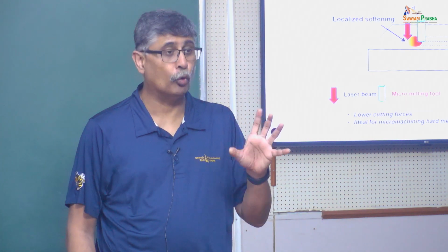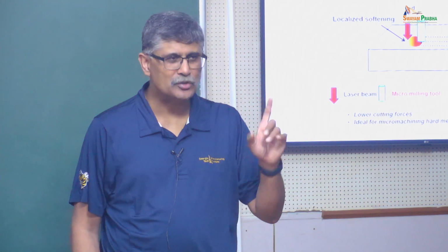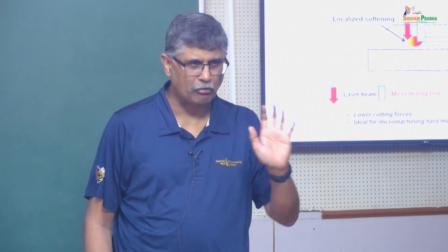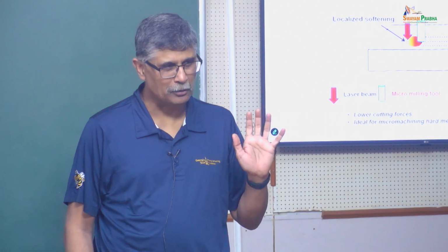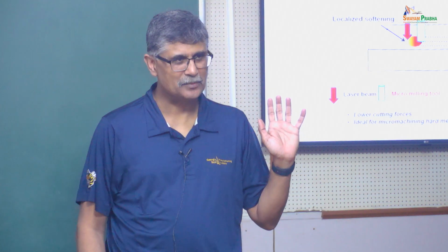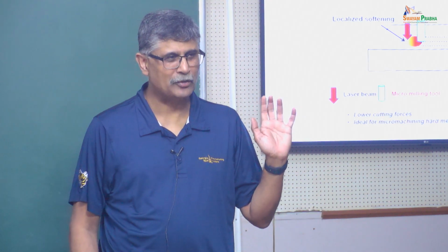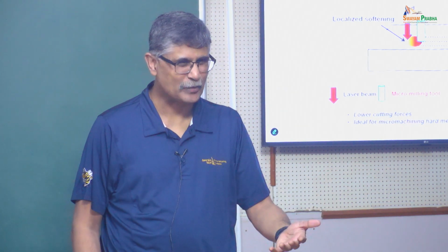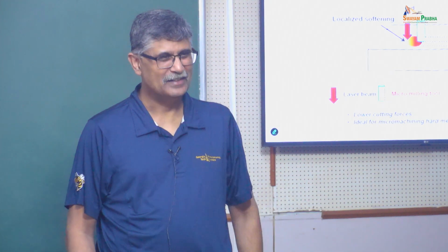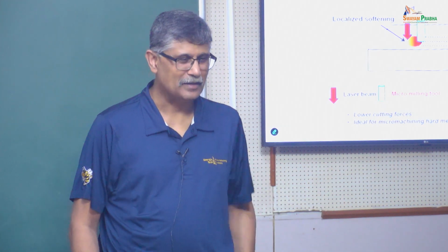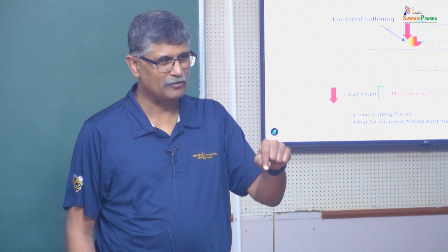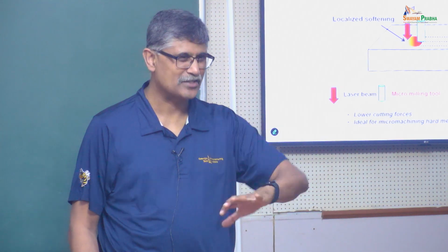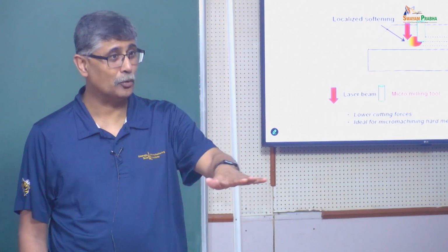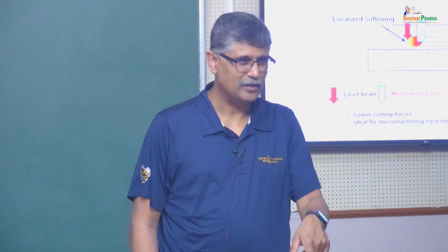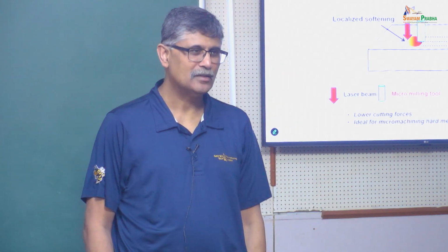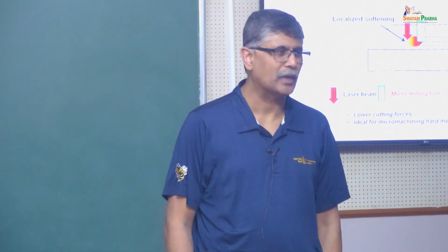If you're doing a hole, it's a drilling process. So you can't really use this configuration at all. Yes, this is milling. It's milling only. It will not work for drilling, right? Because then how do you soften the material is the question. You have to have the laser pointing ahead of it, and beyond a certain depth, the laser will be occluded by the surface surrounding the hole. Yes. You won't be able to irradiate the bottom of the hole. So you really can't do that with this process.